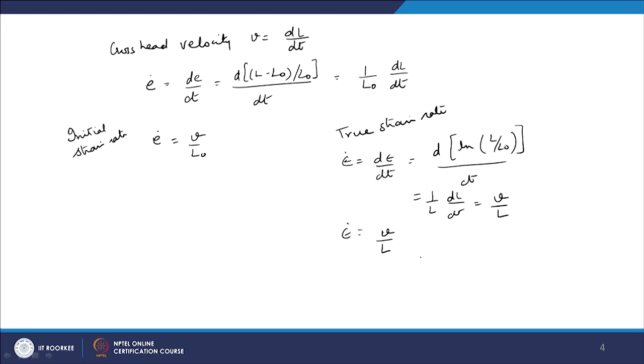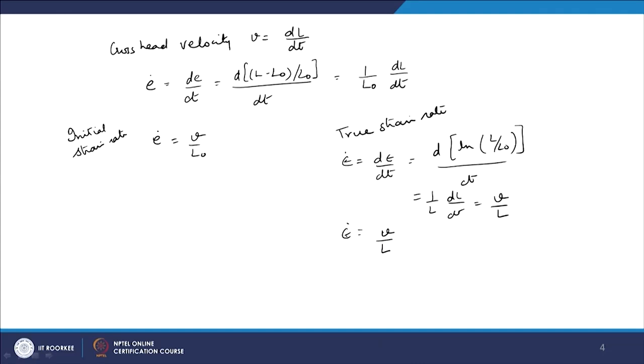So, to have this kind of constant true strain rate, your machine has to be a closed loop servo hydraulic machine. That means it is continuously feeding the machine the change in the length, or change in the extension. To maintain the true strain rate constant, since my length is continuously changing, my velocity also has to continuously change. Whereas in this case, my velocity will remain constant because my L naught is constant. So, I will have a constant engineering strain rate. But here it has to continuously change the velocity as the deformation progresses.